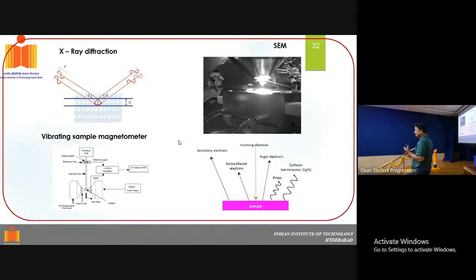Because there will be characteristic X-rays for individual elements. These characteristic X-rays will have particular energy. So those energies are fingerprints for the particular element. So from the energies that you obtain from different X-rays, you can actually identify which element is present in the material.